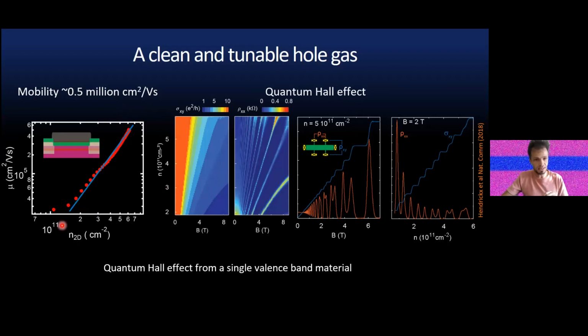However, you can already see in this plot that there were things to improve because the lowest density we could achieve was still quite high, in the order of 10 to the 11. And this is another critical parameter that qualifies the qubit environment, the percolation density. But nevertheless, we were really excited. We got a really textbook quantum Hall effect, fully tunable by gate. And most important, you simply look at these traces and recognize this is a single band material. So you really have this splitting of the energy levels that you were after.